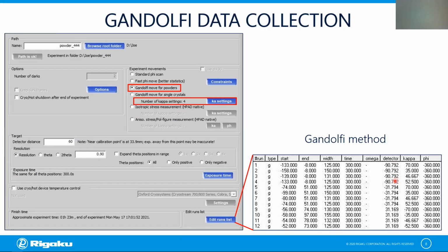Then for each one of these detector positions, there are 4 kappa settings, or kappa angles, associated with a different kappa angle per scan. And that's what will give you the better data randomization. The next thing to be aware of is that both phi and omega will rotate at the same time. On the right-hand side box, you see that a full 360 degrees rotation along phi is scheduled. And on the right-hand side box, you see the rotation range along omega set up for each scan.